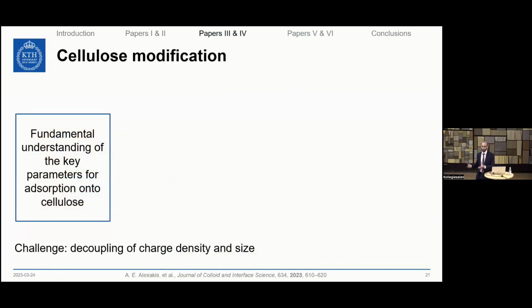Now that we know how we can tune these morphologies of PISA nanolatexes on demand, we wanted to investigate and understand better how we can optimize our system in order to affect and influence its adsorption onto cellulosic surfaces. In the literature, this has been studied quite a lot. However, the main challenge has been how you can decouple the parameters of charge density and size of nanolatexes, because these two parameters are interconnected. By increasing the size, you usually decrease the charge density of the nanoparticles that you use. Fortunately for us, by using this RAFT-mediated PISA technique that I explained earlier, we were able to decouple these two parameters and study them separately.